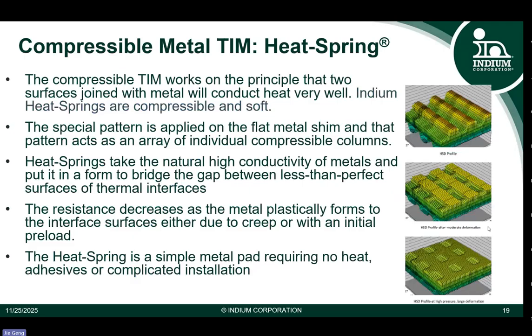So another category is the compressible metal TIM. So actually, it's indium foil with patterns on one side. The patterns, we can change the shape and also the height of the profile. The advantage of this kind of material is you don't need to reflow it. So just clamp it between chip and heatsink with pressure. And the pattern can help to fill the gap at the interface. So the resistance is usually decreased with the metal plastically formed at the interface.